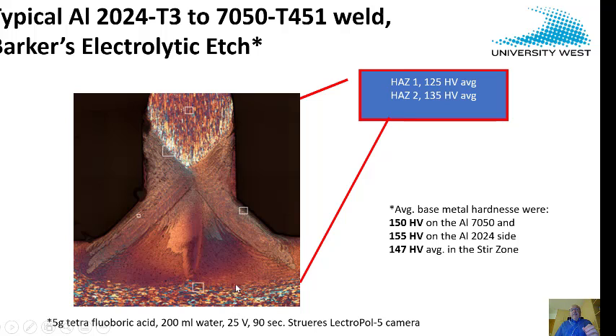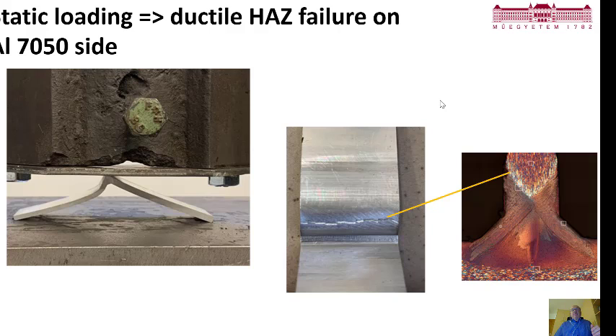You can see that the stir zone has very interesting appearance, yet it has very uniform hardness, about 147 Vickers. The two heat affected zones are softer, about 125 on the 7050 side relative to the 150 base metal, and here's some heat affected zone, also some weakening there, 135 Vickers, but that's tremendously less than you would expect in the laser weld, fusion weld, or anything. Very beautiful pictures.